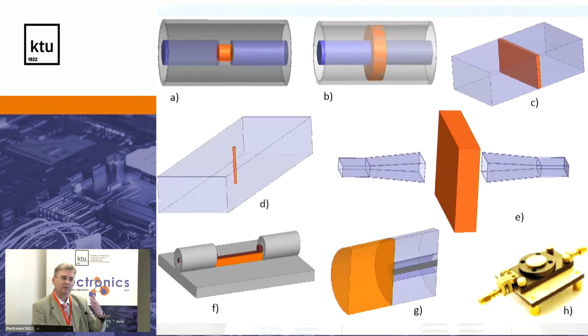The problem is that for capacitors in electronics, as I mentioned, barium titanate is used, and of course capacitors are better when smaller and with bigger capacitance. This means that the electric permittivity must be as high as possible. And when you have a high dielectric permittivity material, this method is not working because, again, from Maxwell equations, it's very clear to see that you have reflection close to 1, transmission nearly 0. And from such data, to extract material parameters is impossible.